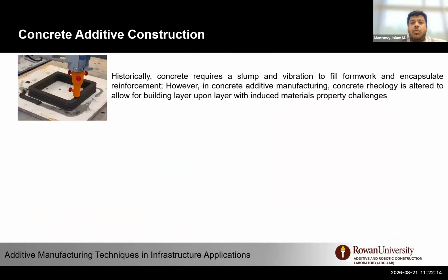So just to introduce concrete additive construction in general, as you know, historically concrete requires slump and vibration to fill formwork and encapsulate reinforcement. However, in concrete 3D printing, we are actually changing the material, and especially the rheology of the material is altered, allowing us to print layer by layer. And that actually induces challenges, especially in the material itself or the structure as a whole.